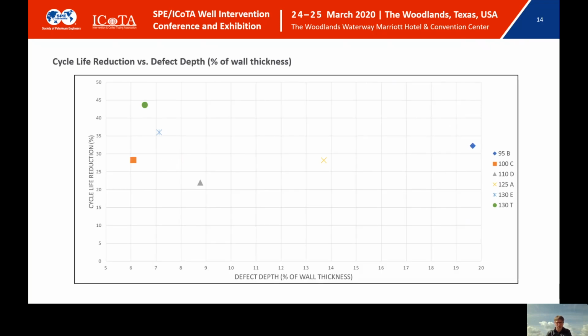Then we looked at the cycle life reduction as a function of defect depth. Because the wall thicknesses weren't consistent, we expressed defect depth as a percentage of wall thickness instead, thinking that might be more meaningful. And again, no great correlation there. But of course, it's still cycle life reduction on the vertical axis, so that 20 to 45% still continues to jump out.